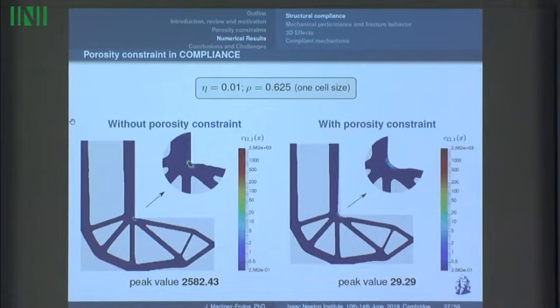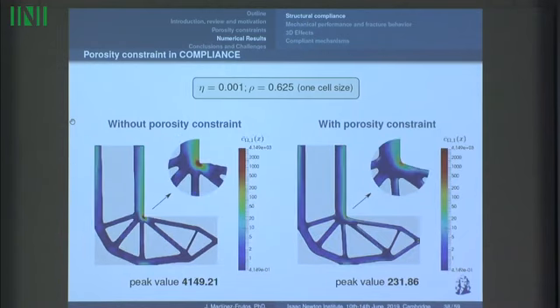We can also reduce this parameter eta to give the porosity more importance in the design, and we have this result. In this result, we see that the regions that are sensitive to the porosity are larger, and as a consequence, we also have a larger radius of this corner compared to the previous one. And we also see this reduction in the peak value again.